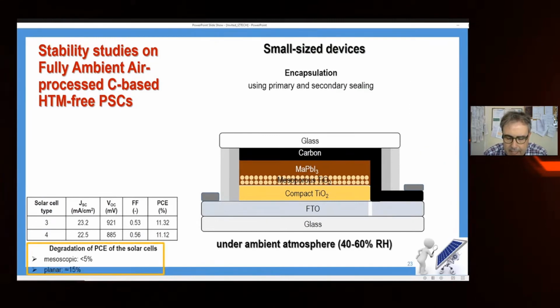We notice some degradations basically at the first stage because the thermoplastic material is processed at 150 degrees, which sometimes causes some problems with the crystallization of perovskite that we use at 100 degrees. So for the mesoscopic structure, we measured a 5% decrease in the overall efficiency, but for the planar, we measured approximately a 15% decrease after this treatment.